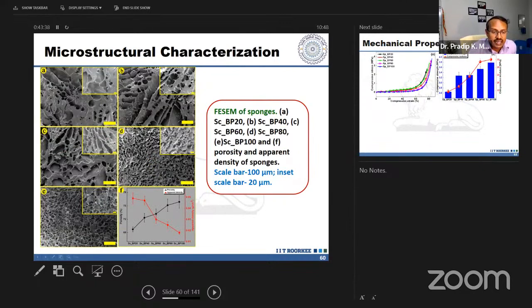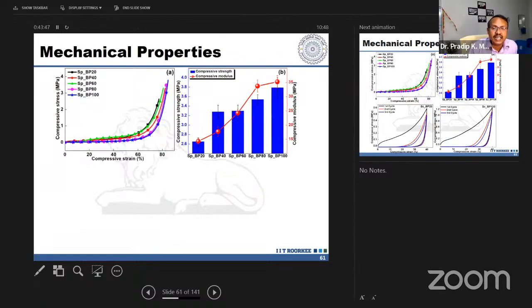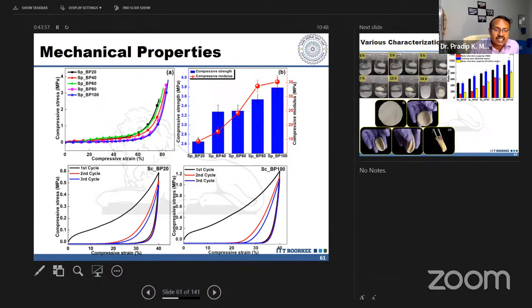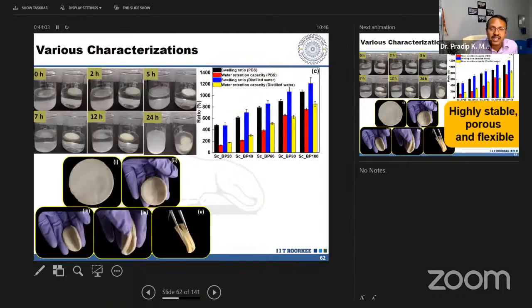This is the morphology. If you see, the morphology is very good, and it's almost similar to what we have shown earlier. There is not much change. But one important thing is that the mechanical property is going to increase a little bit. The compressive strength increases slightly compared to earlier, and the cyclic strength is also 40%. We are getting very good recoverable property.